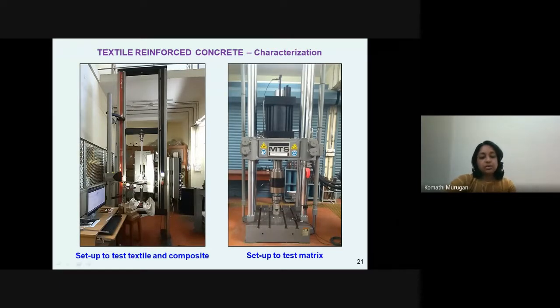So these images here show the setups which are used to test the textiles and composite. The first picture here shows the electromechanical test device, which has a capacity of 5 to 50 kilonewtons, which can very refinedly and critically test the textile reinforced concrete panels or the textiles itself under tension or tensile load. The second image shows the servo controlled hydraulic test systems, which are used to conduct the displacement control test for the matrices which are used for these applications. So what we get is the post-peak behavior of the matrices as well. Both of these are displacement control test systems.